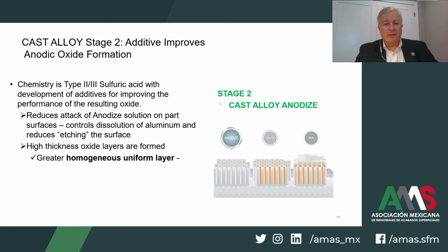The additives we designed work to modify the oxide microstructure by increasing the number of smaller pores, packing them in a tighter, more consistent order, which offers a better defined, more homogeneous, uniform structure. That's very critical for the overall success. We achieve a higher oxide surface gloss. We get a smoother surface finish of the oxide layer, which contributes to improved anodized functionality of the surface. That includes wear performance, hardness, and surface finish, including the brightness and the smoothness.